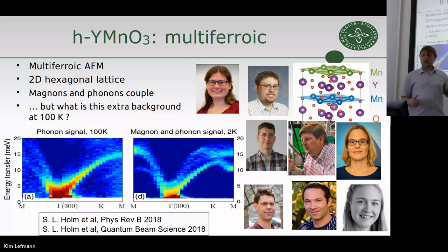But see here, there is an avoided crossing there. So this shows the coupling between the lattice vibrations and the magnetic vibrations due to the multiferroic nature of yttrium manganite. So does this have a specific name? Because like in the light-matter interaction, we call this a polariton. And how do you call this interaction? Sometimes it's called an electromagnon, but only if they really coincide for a long time. This is actually just this particular case. So we don't have a particular name. I just call it a band crossing. I hate using too fancy words about things that have an easy explanation.